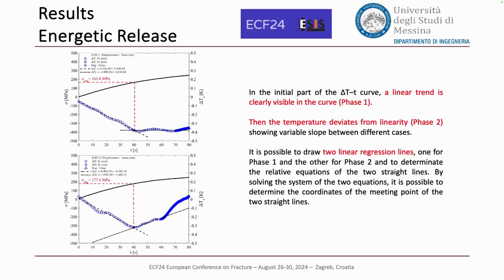Here are the results related to the static thermographic method, so the energetic release of the material. According to the theory, in the initial part of the delta T curve, a linear trend is visible. Then the temperature deviates from linearity, showing a variable slope between the two different cases. It is possible to draw a linear regression and determine the coordinates of the meeting point of the two straight lines. But we have to notice these two steps that may raise some doubts, because the intersection between phase 1 and phase 2 could also be associated with it.